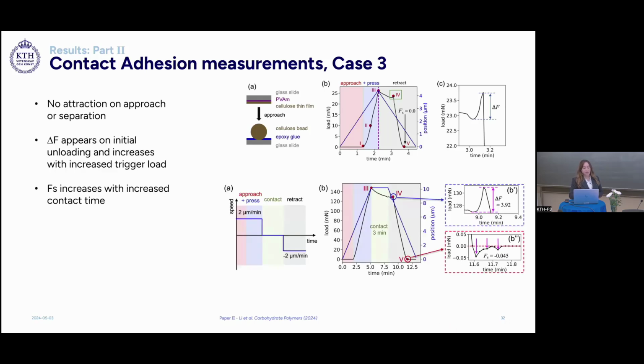Now looking at case 3, where we have a cellulose bead, again measured against a cellulose film spin coated on a glass slide, we can see that there's no attraction or separation. However, there's a different behavior where we see an increase in the force where we start to unload the two surfaces. And this force increases when we increase the contact time between the surfaces between unloading. We also have a separation force when we increase the contact time.